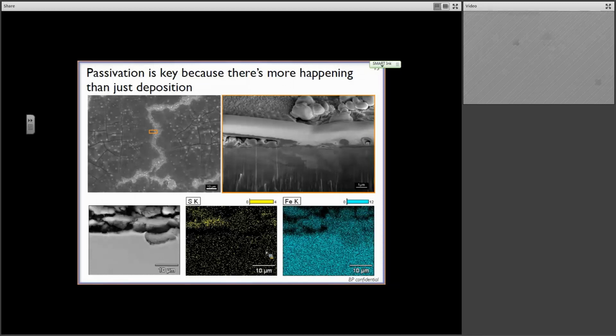And so if we take one of these heavily fouled surfaces, in this particular case I'm showing you an example of the X65 that has been polished to a smooth finish. And so we have these big island-like deposits with all of the mud cracking, and in between there are these kind of globular sorts of regions. What we did is we zoomed into this little orange box here, and we did a FIB cross-section there just to kind of get an idea of what's going on. Is this a continuous layer of carbon-based material? And what we see here is that these continuous areas, the big ones that we see over here, these are continuous mats of carbon-like material going on here.